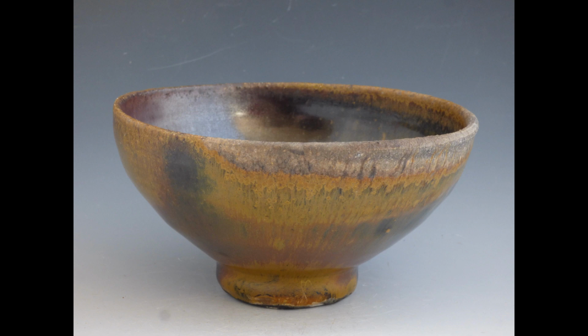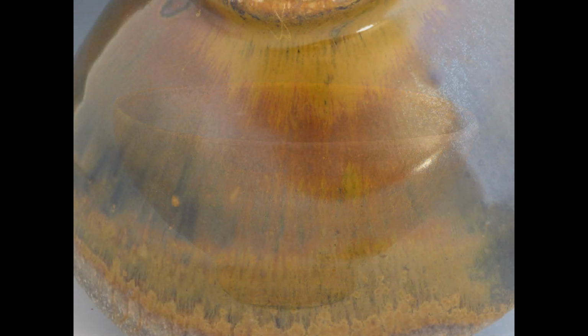Here's another example of an Oni Temmoku tea bowl. You can see the black quality of the glaze inside the bowl, right in here. And then it's just glazed with Temmoku, and all of these colors and textures are brought about by the interaction with the fly ash from the fire. And here's an example of that kind of beautiful, almost vibrating and iridescent yellow gold, very gorgeous color. Now this only occurs in the very back of the kiln as well. This has to happen towards the very back of the anagama, and in this case preferably up towards the top of the anagama, way out of flame reach, but still needs to get some ash.